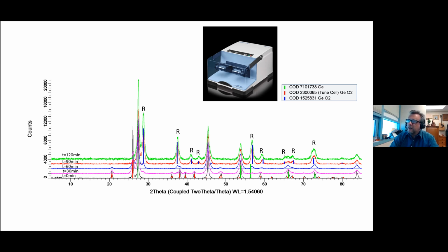The grinding was performed in this oscillating mill. The energy is controlled by choosing the frequency of oscillation. We performed this experiment at 30 hertz. And you can see the results. You can see that right after milling for about 60 minutes, about 1 hour, we have first peaks of the high pressure phase, the stishovite phase, that form. And eventually, after about 2 hours, the initial quartz phase disappears completely.